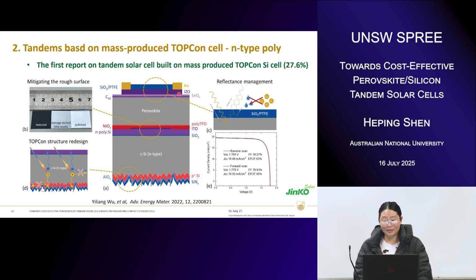We did this work in collaboration with our industry partner Jinko Solar. Basically, we grabbed the silicon cells from their production line, and we developed the perovskite on top of it for the tandem. So at that time, we started by demonstrating tandems on the planar structure. Although planar, they are not planar like our lab-level planar. They are still quite rough.